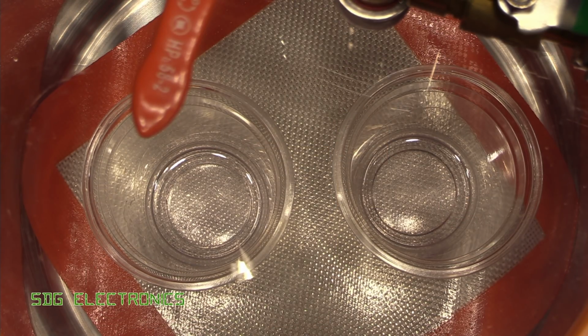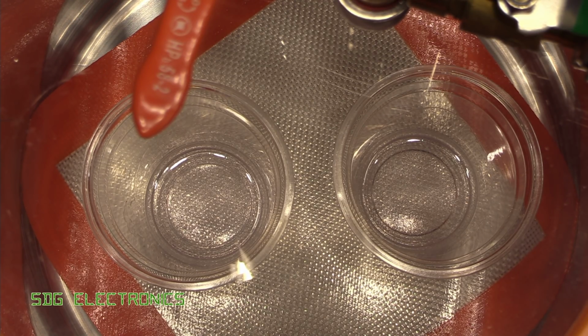Right, so we're just drawing down a vacuum again. And the key here is to make sure that you don't mix the resin with too much hardener, because you do want to allow about 10 or 20 minutes in the chamber to get rid of all of the bubbles.